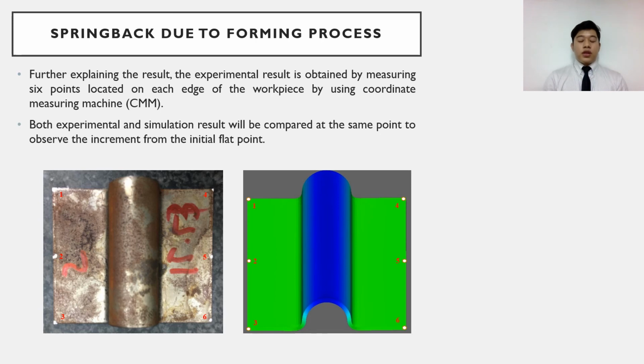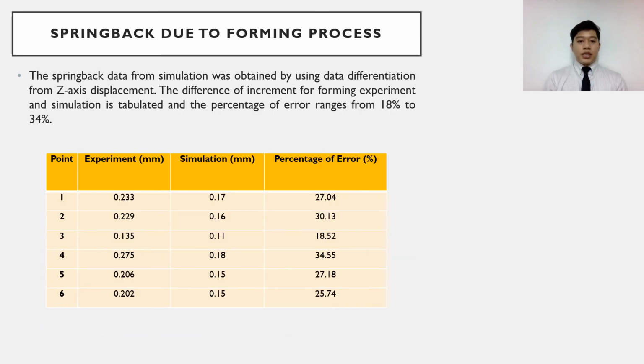To further explain the result, the experimental result was obtained by measuring 6 points on each edge of the workpiece using the CMM. Both experimental and simulation results are compared at the same points to observe the increment from the initial flat point. These are the results for the 6 points, where the percentage of error ranges from 18% to 34%.